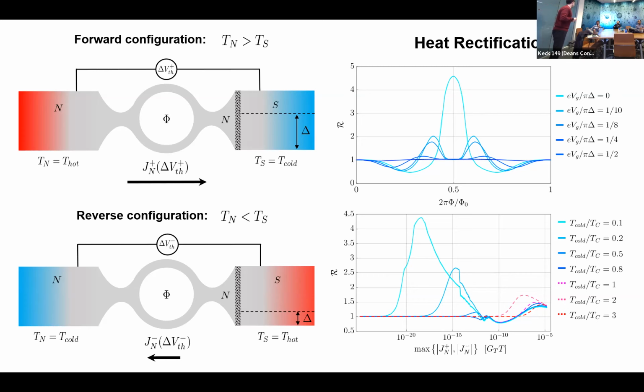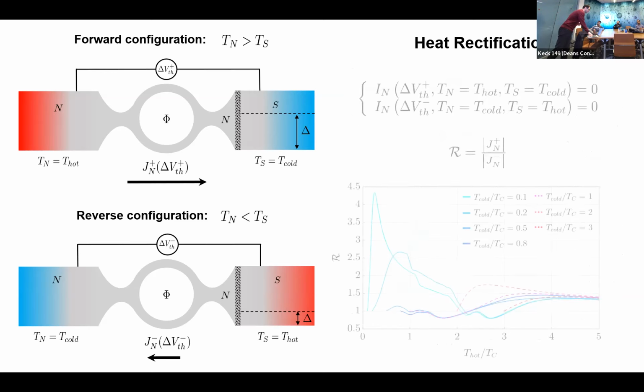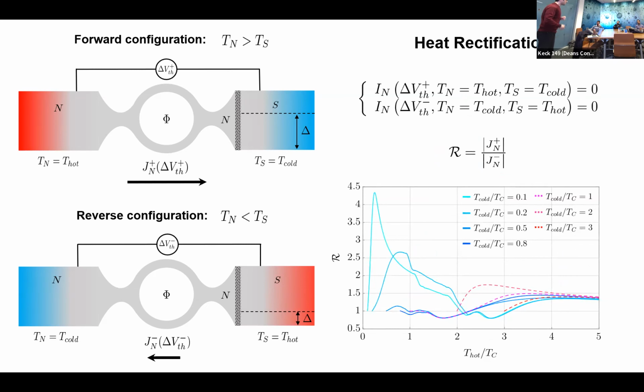If I understand correctly, the rectification you obtain is not just because of left-right asymmetry; you have to have some kind of symmetry breaking in the middle as well, right? You have to, because if you just have a quantum dot in the middle and just put different resistances, you never get a rectification, because the transmission probability is a symmetric factor of gamma L and gamma R. You also need some kind of nonlinearity in the system. And it looks like you have to modulate either phi or Vg to get that nonlinearity. Because for Vg equal to 0 and phi equal to 0, I don't think you get rectification.